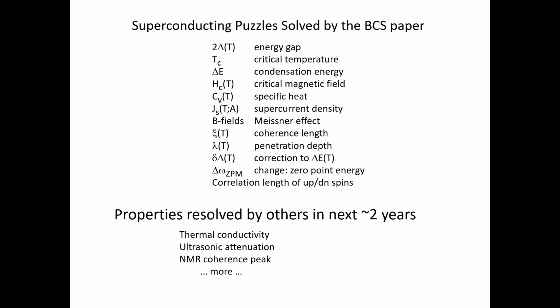And the BCS theory explained about a dozen properties that had been measured of superconductors. It was amazing. And it's still the most widely used and referred to theory of superconductivity now. And within 2 or 3 years after 1957, even more properties were checked that were predicted by the theory, such as thermal conductivity, ultrasonic attenuation, and so forth. Also, when you look carefully, you could see the superconducting transition temperature effect there.